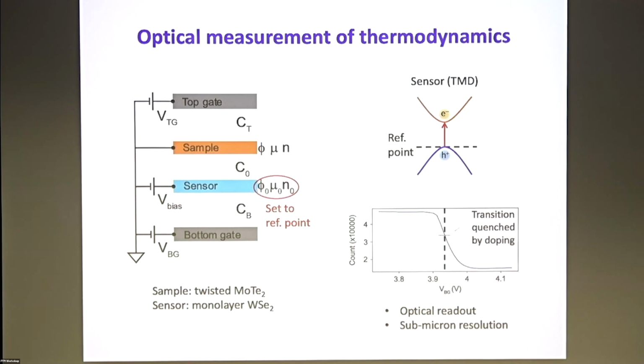Yeah. There's no exciton. Huh? There's no signature of exciton on objects. Yeah, actually, this is really looking at the exciton. But also, when you have excitons, this Pauli blocking is not going to be complete. In fact, the excitons will turn into charged exciton resonances. But the neutral exciton, if you look at the particular photon energy, is nearly gone after you put some doping into the valence band. But there is exciton, yeah.